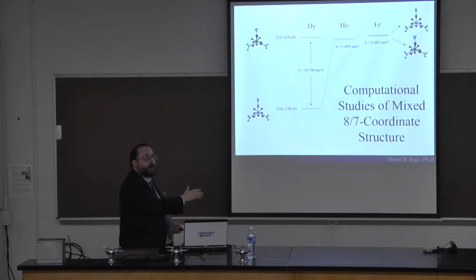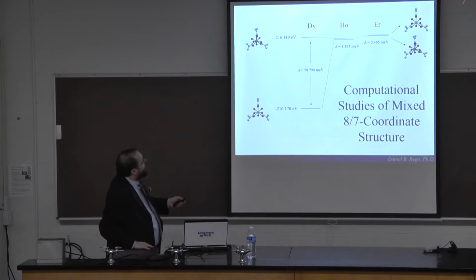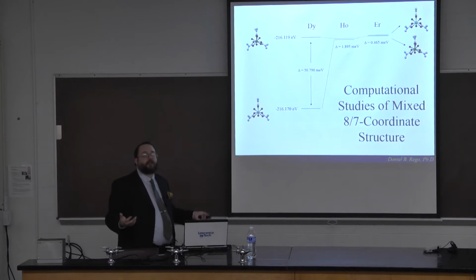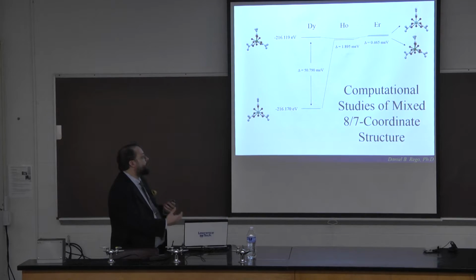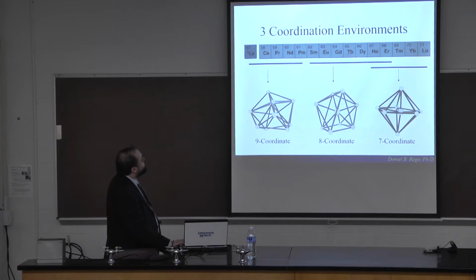I did have some computational studies done on this with a coworker named Zinja Kim, and it turns out that the energy levels between those two structures are pretty much the same. They're degenerate, so it's equally happy to be in each one. Neither one really fits perfectly well, so it sometimes does one, sometimes does the other, and basically tries to do the best it can. So basically, we see the lanthanide contraction at work going from a 9 coordinate to an 8 coordinate, which transitions to a 7 coordinate.